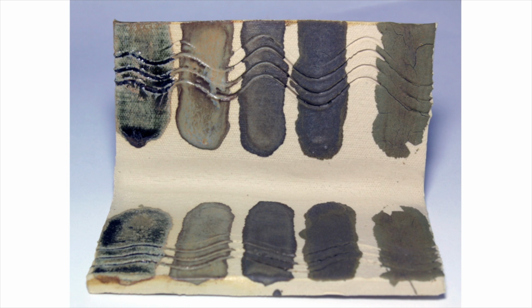After observing the fired test tile, I chose which stripe I liked best. I chose the second stripe in this example with a 10% addition of EPK, which was then added to the 500 grams of the wet slop glaze.